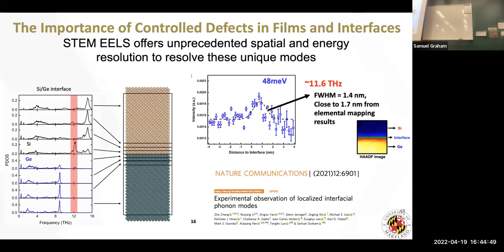And so this is a neural network potential. This is done with our collaborators, Shake and Henry at MIT, and Tianfei Luo at Notre Dame. What they did is they predicted that whenever I take silicon and germanium and put them together, very locally near this interface, all of a sudden I get this peak that doesn't exist in either the germanium or the silicon. There's a new mode that pops up, a vibrational mode. These vibrational modes help to carry heat.